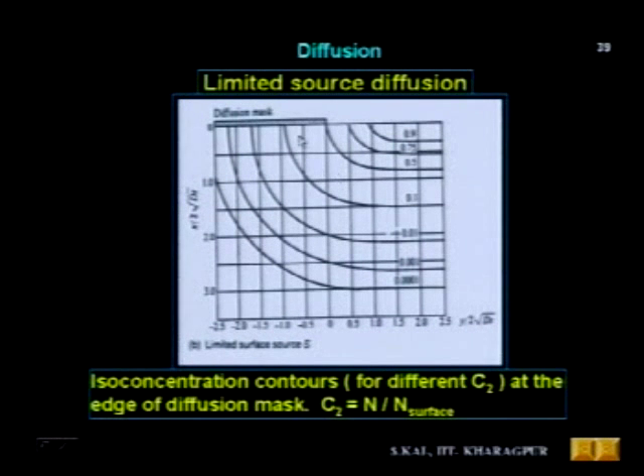Similarly, if you look at limited source diffusion, the doping profile is like this. Here, limited source diffusion means that at the surface the source is limited, and again this is a 2D profile. X is x by 2 root dt and y is y by 2 root dt, and again iso concentration contours for different C2 at the edge of the diffusion mask. You can see here C2 means n by n surface for 0.9, 0.75, 0.5. You see, if you go deeper along the x direction, then obviously the C2 value will go down, and these values are like 0.9, 0.75, 0.5 like that. These are the iso concentration contours for different C2 values.